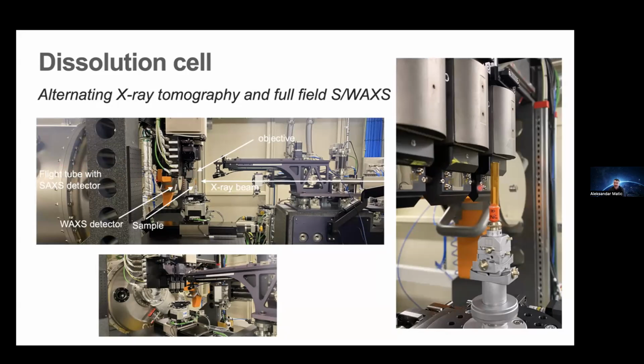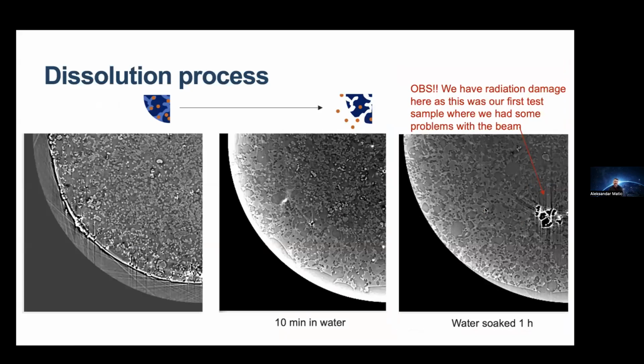And here a zoomed-in image of our sample again. And to the left here, now we are looking at a slice through our strand. So imagine you have your spaghetti vertically, and you just take a cross-section through it, like a horizontal slice through it. So imagine you're looking here at the small part of the sample depicted up here. And this is the starting morphology. And you can see that after some 10 minutes, and then after 1 hour, we create more and more voids. We are leaching out polymer from the sample.